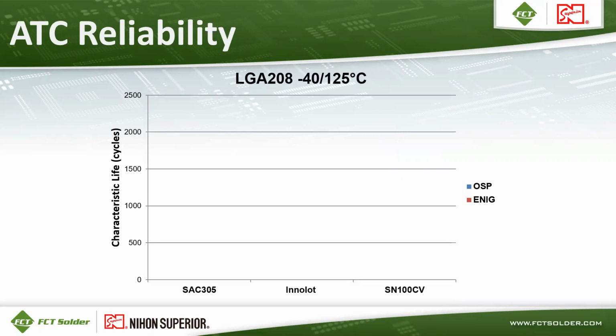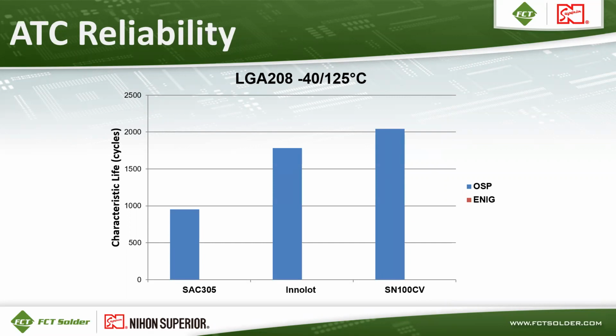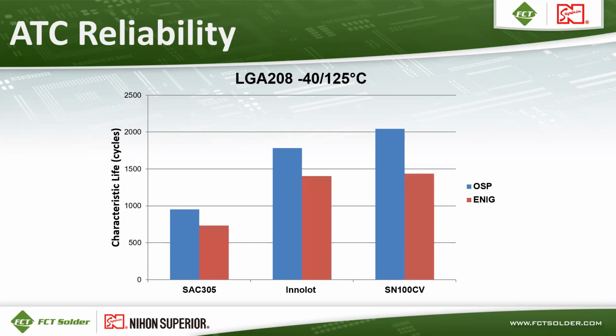Here's that same data for the LGA 208 component for just three of these alloys. SAC 305 in this case is the lowest characteristic life. Innolot was in the middle for that component, and then SN100CV actually has a higher characteristic life for that component on OSP. And then when we ran that test on ENIG, you've got SAC 305 again with the lowest characteristic life, and then Innolot and SN100CV matched each other in terms of life on ENIG.